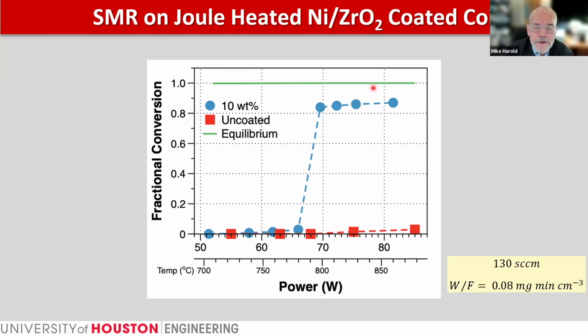Now, there are some notable attributes of these data. First of all, as we would expect, the conversion goes to a high value at sufficiently high temperature. The temperature measured or predicted by that energy balance shows that upwards of 800 degrees centigrade, pushing 900, in that range, the conversion of methane approaches 90%. Now, that is not an unexpected result. We expect an endothermic reaction whose rate increases and whose equilibrium becomes more favorable to have a conversion approaching, hopefully, completion. And with this 4-to-1 steam to methane ratio, the equilibrium is favorable.